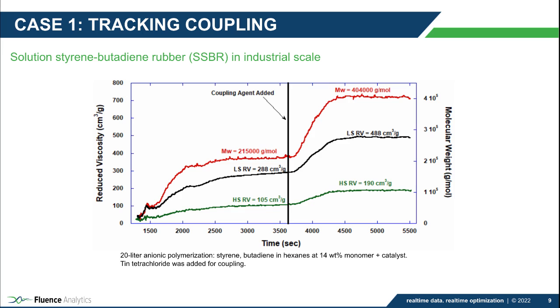Up to 3600 seconds into the reaction, what can be seen is the natural increase in the polymer chains as the reaction progresses, which is consistent with monomer consumption and shows the living character of the reaction, a monotonic increase in signals as the propagating chains are alive. After the coupling agent is added, the second half of the reaction shows another significant increase in these values, consistent with these polymer chains formed before being brought together through coupling, quickly reaching their final specifications of molecular weight.